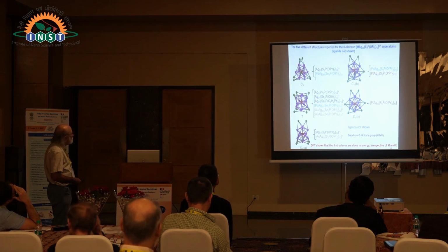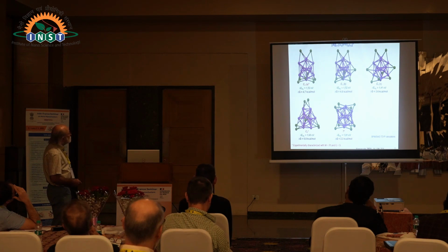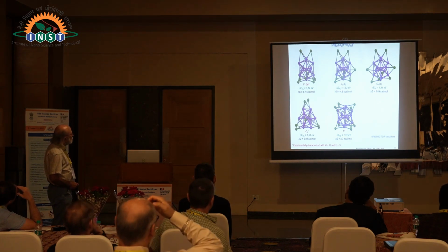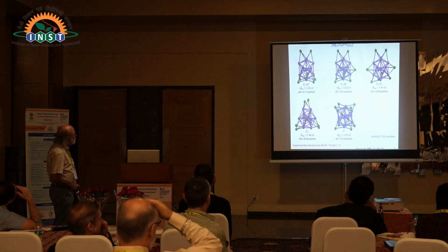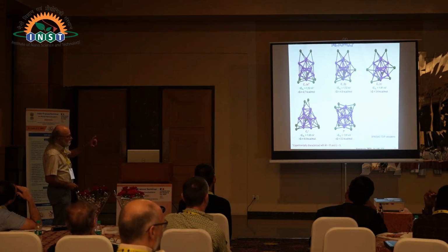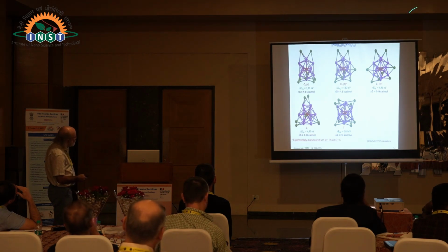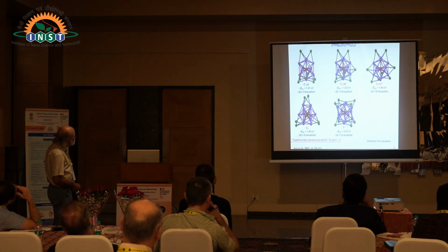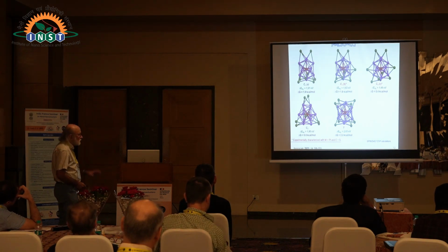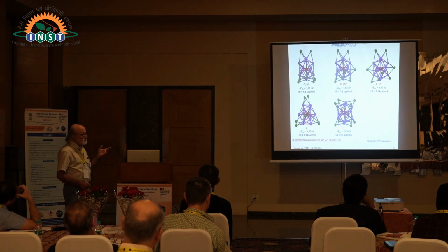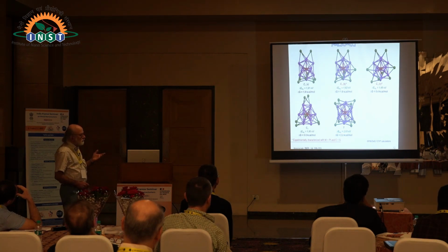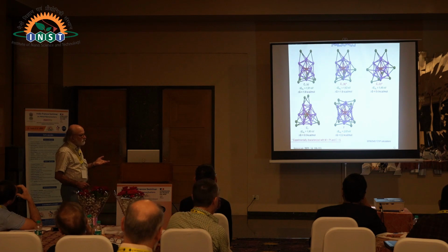There are more. Just to show you, the homometallic system with 21 silver atoms, the 5 structures lie within the range of 5 kcal per mole, approximately. In the case of the platinum-centered, they lie within the range of something like 2 kcal per mole. 2 kcal per mole is not significantly different from 0 at our level of theory and modelization, actually.